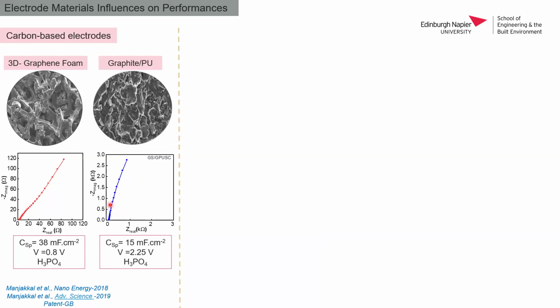For example, in a graphene foam device I got, you can see from the impedance spectroscopic analysis that the resistance is in a very low range. That means it's a better electrolyte interaction. But the energy storing of this electrochemical double layer is very limited, and I observed the specific capacitance at 38 millifarad per centimeter square, but the operating voltage is limited.